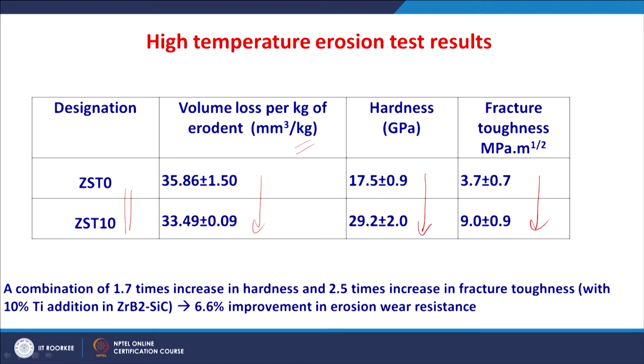But this combination of increased mechanical properties resulted in only 6% or 6.6% improvement in the erosion wear resistance. So, there was a large improvement in the mechanical properties by adding 10% titanium in the zirconium diboride silicon carbide composite, but this reflected in only 6.6% improvement in the wear resistance. This is very interesting. So, this is where we need computational analysis to understand such behavior.